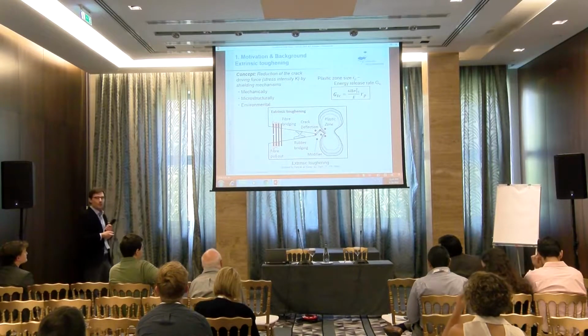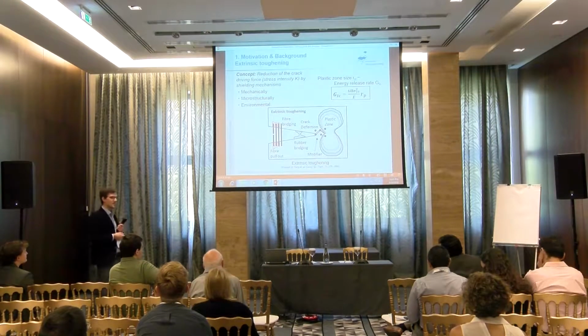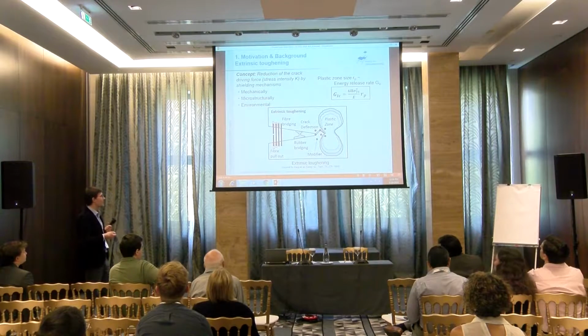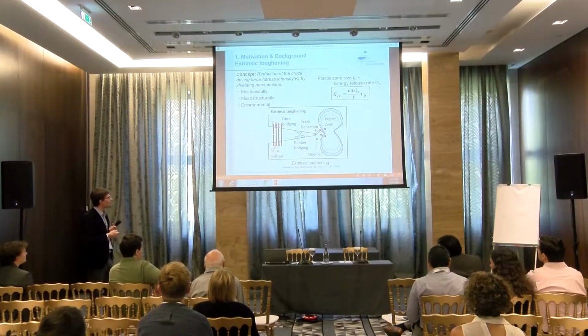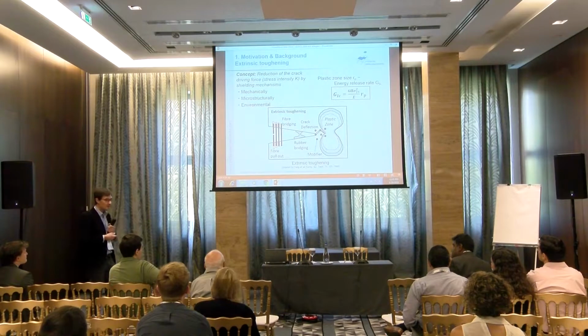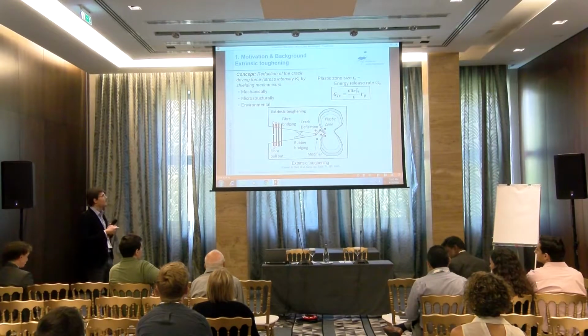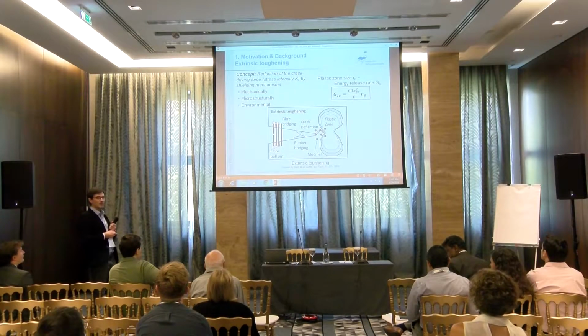In the morning we heard from Professor Ritchie already about the extrinsic toughening, and that's actually the approach we are following as well. Toughening of polymers, epoxies can be done by adding second phase modifiers. They work in different ways. So for example, rubber can bridge a crack, right, and close the crack mouth more or less. Then we have more inorganic or rigid particles which lead to a crack deflection mechanism. In the end, everything is related to the plastic zone size. So if we can increase the plastic zone size, we can increase our energy release rate of the material.